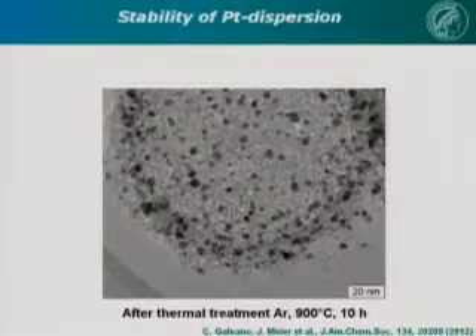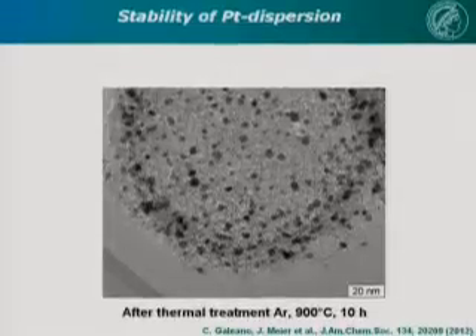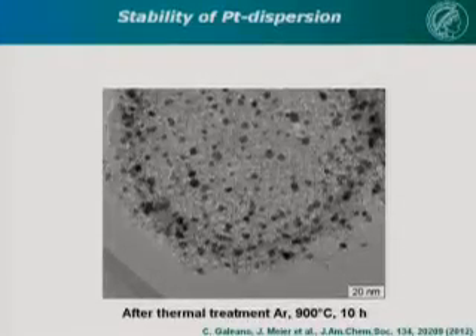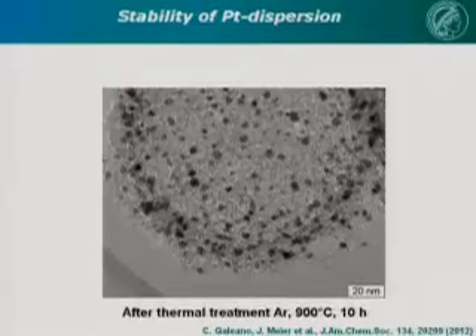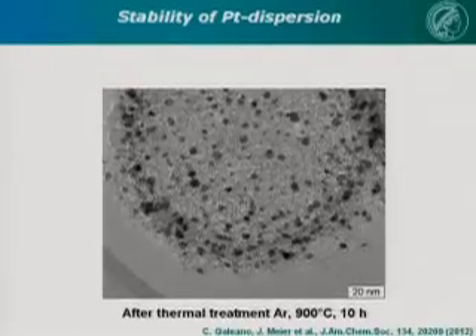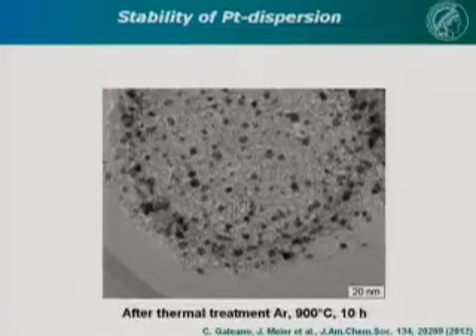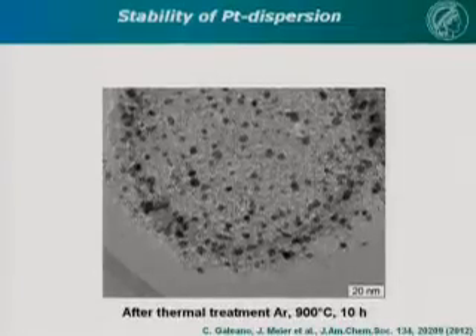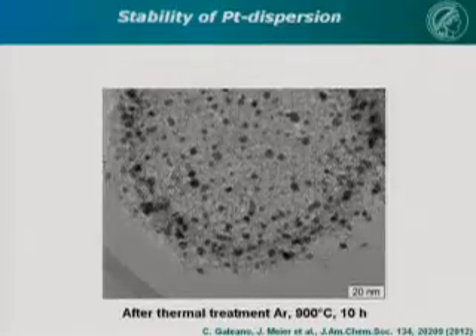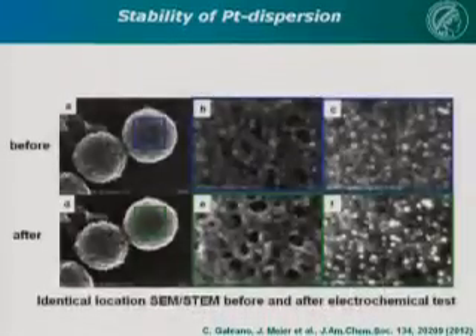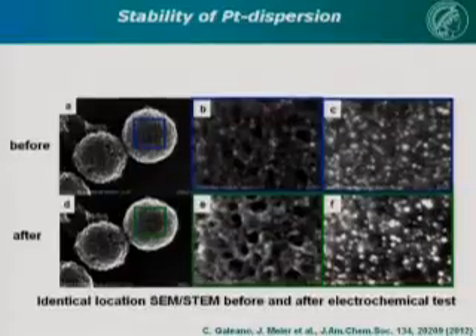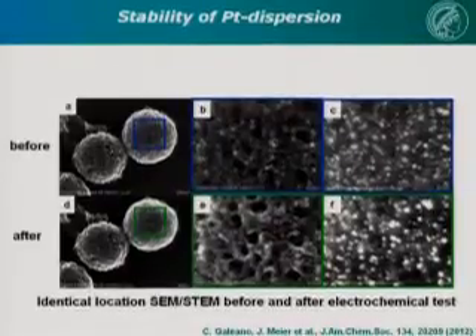This is platinum on this highly graphitic carbon shell after treatment at 900 degrees centigrade for 10 hours. So this is really a harsh treatment for a platinum catalyst. And you see platinum particles are, well, between 3 and 5 nanometers in size. They don't grow bigger than that. And this is ideal for fuel cell catalysts. And they are actually stable under the conditions of the fuel cell.